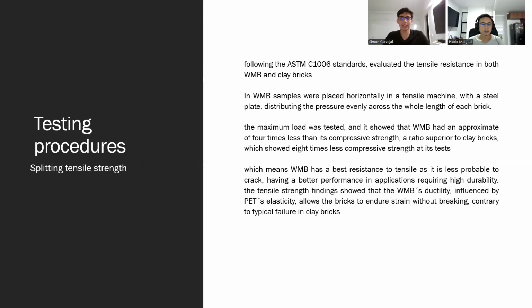So now for splitting tensile strength, the WMB samples were placed horizontally in a tensile machine with a steel plate, distributing the pressure evenly across the whole length of each brick. The maximum load was tested, and it showed that WMB had approximately 4 times less than its compressive strength, but clay bricks showed 8 times less than their compressive strength. This means that WMB has better resistance to tensile strength and is less probable to crack in comparison to clay bricks.